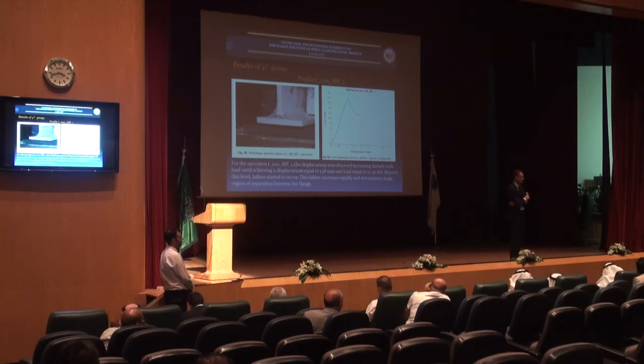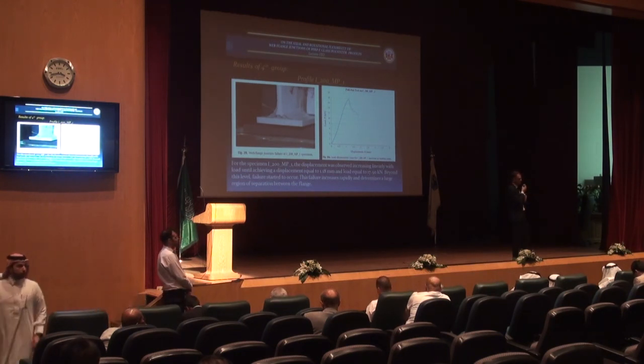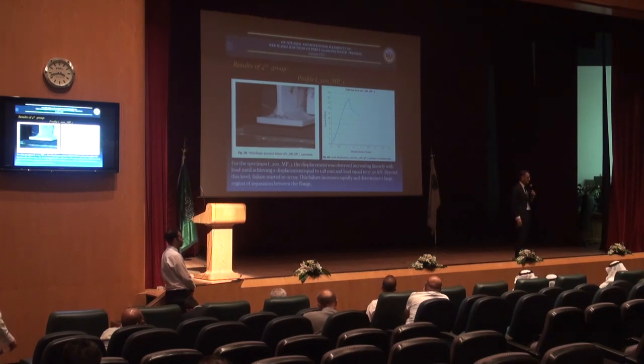Yes. Good question regarding the finite element model. How did you model the FRP, as elastic material or inelastic material in the finite element? We developed it as a transversely isotropic material with 5 different constants. In particular, you have 2 elastic Young moduli, one in the longitudinal axis and the other in the transversal direction. You have 2 shear moduli and 1 Poisson ratio. This is due to the transversely isotropic hypothesis. But in case you don't have this behavior, you need 9 elastic constants: 3 Young moduli, 3 shear moduli, and 3 Poisson ratios.